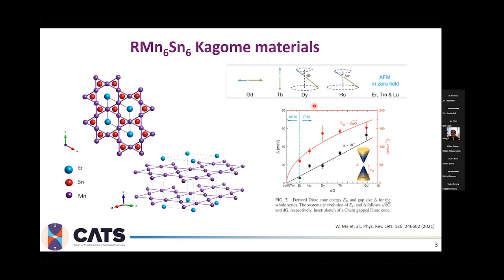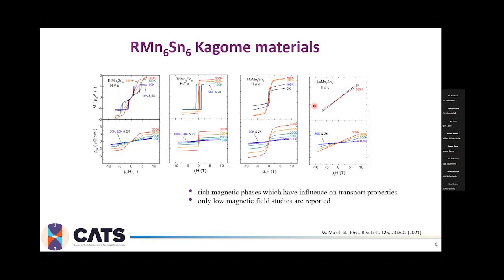What we can see is that the manganese forms the kagome lattice, which is separated by the rare earth ion. And the interesting point is that we can see a variety of ground states, from gadolinium and terbium, which are ferromagnetic, ending on erbium, which shows an antiferromagnetic ground state. There was also some prediction about how the gap and the Dirac cone depend on the rare earth ion.